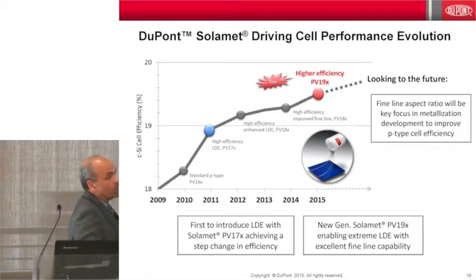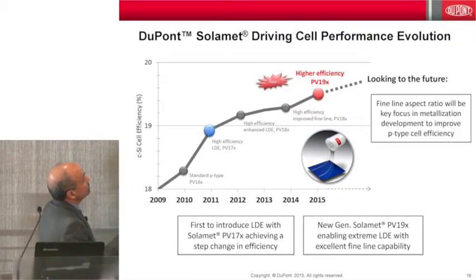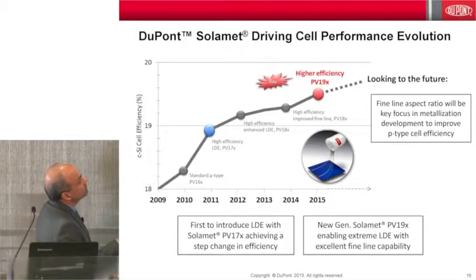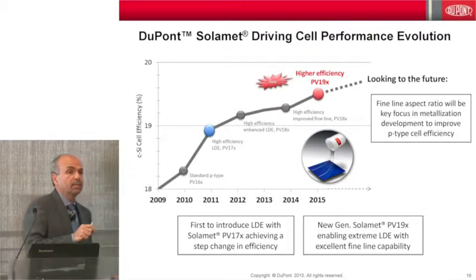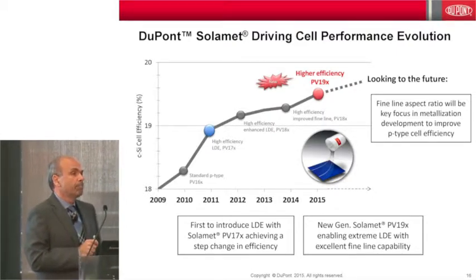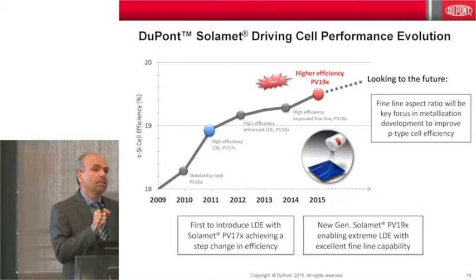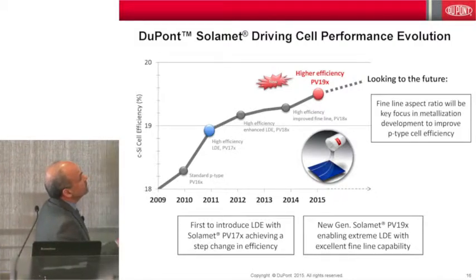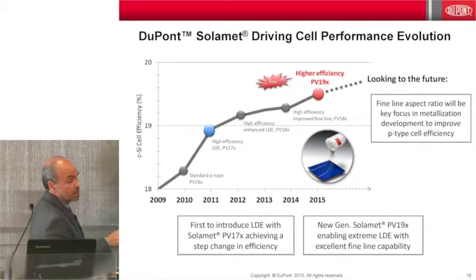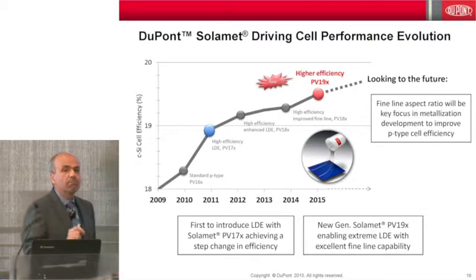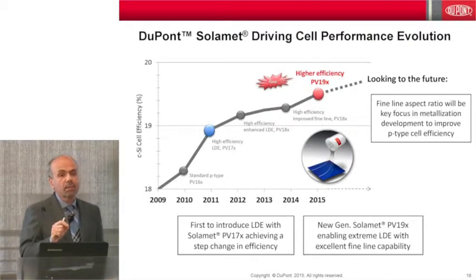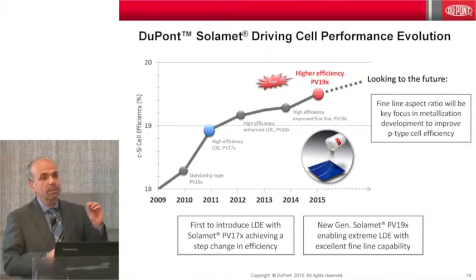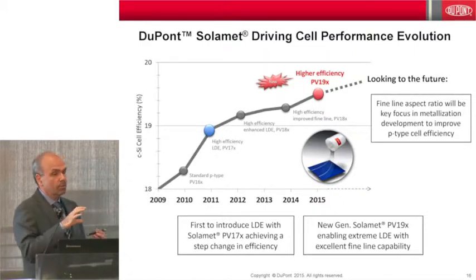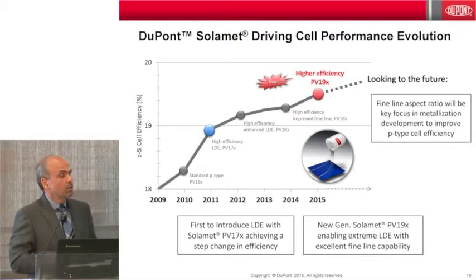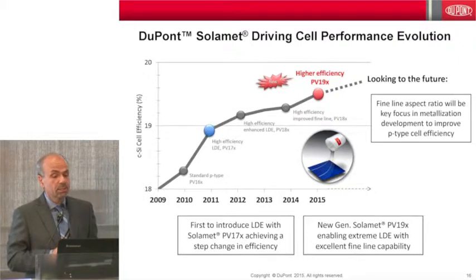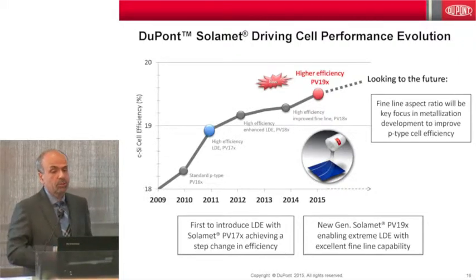What you see there is the progress in crystalline silicon cell efficiency the past 5 or 6 years, based on the front side silver paste. It's something that most of the industry doesn't know, but the majority of the progress in cell efficiency, we started around 18% at the cell level, and now we are at 19.5. Primarily, this progress has come as a result of tuning the silver paste in conjunction with the doping concentration of the phosphorus on the top surface of the crystalline silicon. And I will say a few words on how we do this.